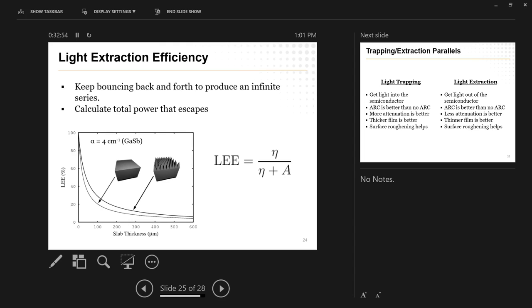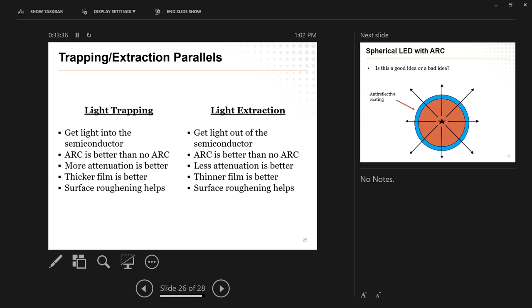So the take-home point, though, is that as your slab gets really, really, really thick, you know, half your energy just falls out to the bottom, and your light extraction efficiency tanks, and it all just gets absorbed. Whereas it gets very, very thin, and eventually shoots up and you get very close to 100% of your light extraction efficiency. So for example, a typical wafer of some semiconductor like this might be anywhere between 5 to 10 to 50 microns thick. So you're down here, now you're getting 40 to 50 to 80% of your light extraction efficiency. So it's the same idea of that Yablonovitch limit, where you're trying to bounce light around to get it to absorb. Now you're trying to get that light to bounce around and eventually get out into space. And you can reach pretty respectable numbers again by following that same idea.